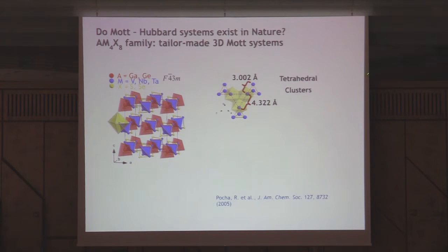If you do the electronic counting, you find out that you're going to get 1 remaining electron per tetrahedron. And then the hopping between these tetrahedra is very small because they are far. Moreover, all this thing is an FCC lattice. All the blue tetrahedra form an FCC lattice, full of these triangles. So that fully frustrates the system, and the system doesn't want to order. So since this does not want to order, this thing will not have a strong tendency to antiferromagnetism.